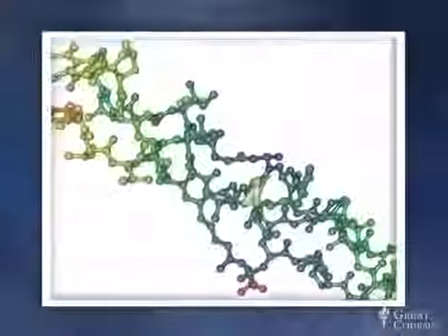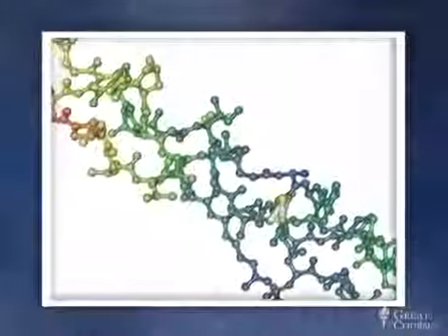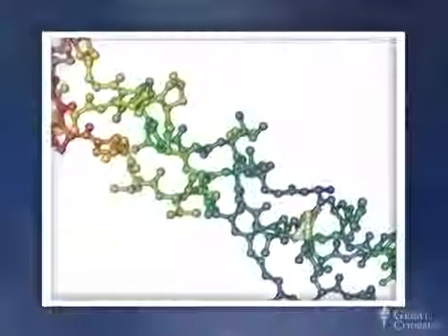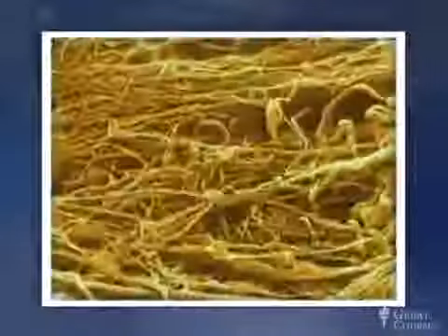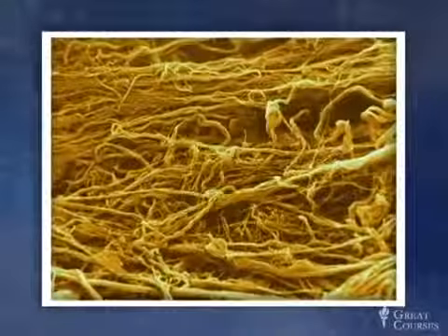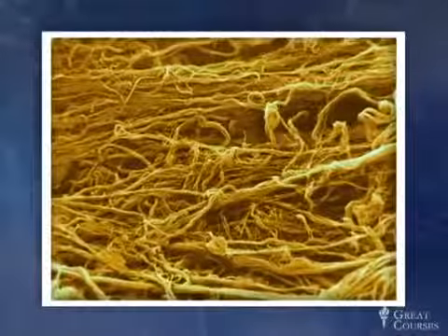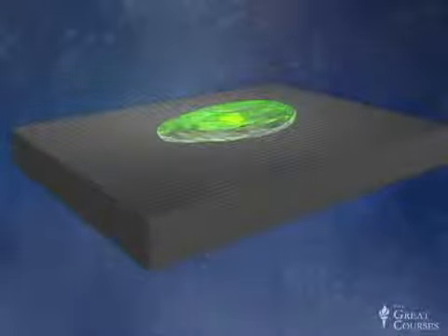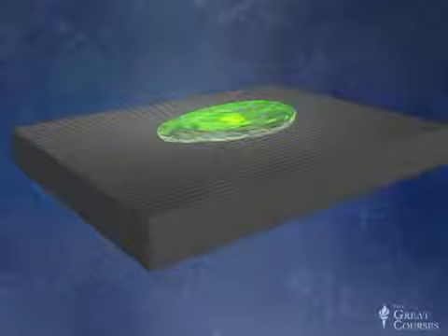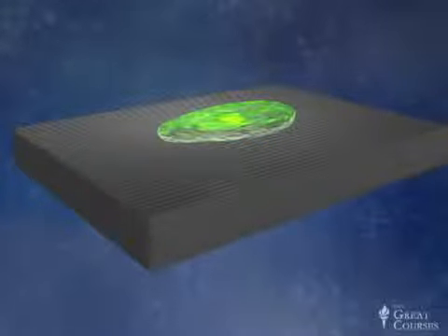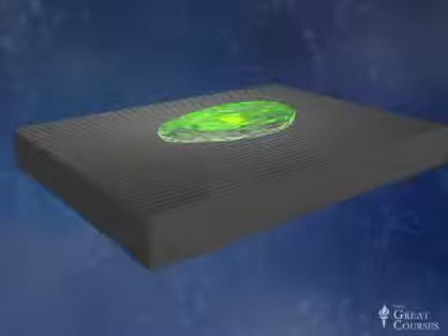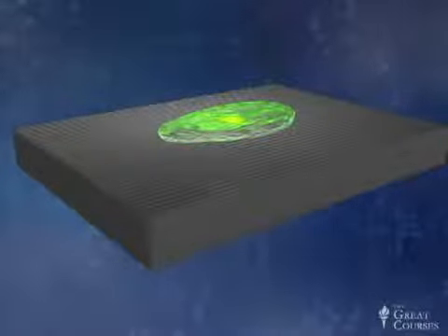The relationship between collagen and nanoscience is that this protein has been used as a model for the development of nanomaterials that can support cell growth. As we just discussed, collagen is oriented in fibers, and its directionality and the spacing of the fibers tell cells how to position themselves. And this natural phenomenon has been mimicked with nanomaterials. Researchers at the Massachusetts Institute of Technology have produced nanoscale gratings that mimic the structure of collagen. And they found that these gratings are effective at orienting cells.